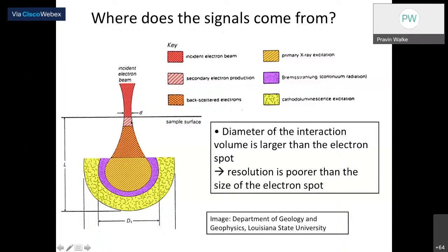So here, this incident electron beam interacts with the sample. What happens close to the sample surface? Here you see the incident electron beam. Here you see the secondary electrons generated near the surface. Later on, you will find the backscattered electron region. This is the length, right? This length is you traveling from the sample surface deep into the sample. Very close to the surface there is probably secondary electron production. Later on, you travel some certain distance and you will find the backscattered electrons were generated inside the sample. And beyond that certain length, there is a diameter as well as a length. Here, this interaction volume will give you primary X-rays, right? And then beyond that, you can easily find the continuum radiation in that system, and beyond that, cathodoluminescence excitations, right? So this is how these signals are distributed throughout the specimen when there is interaction of the beam, right?